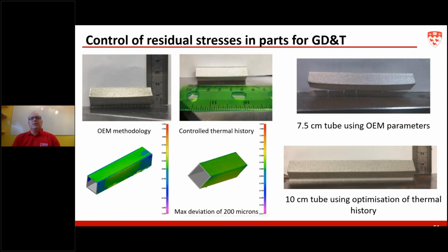I just want to show you here the importance of the control of residual stress. Like welding, the development of residual stress is quite important during processing. And if you cannot control it, you're going to go off the specification of geometry, dimensional, and tolerance. So I'm showing you on the example here, mainly focus on the center part, which is a diamond tube, which seems to be quite a simple shape. It's a very tough shape to fabricate without distortion.